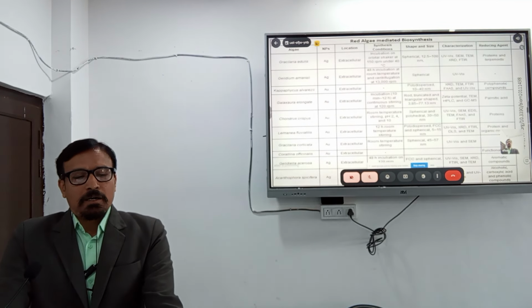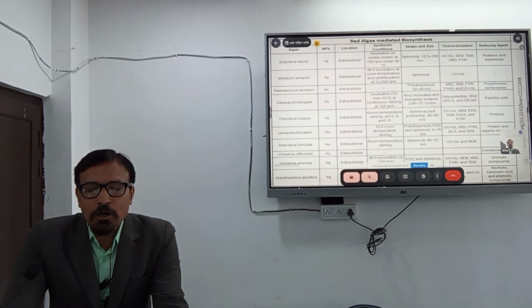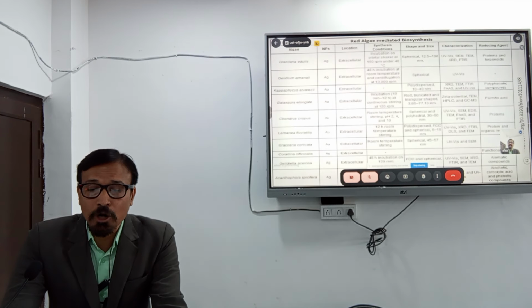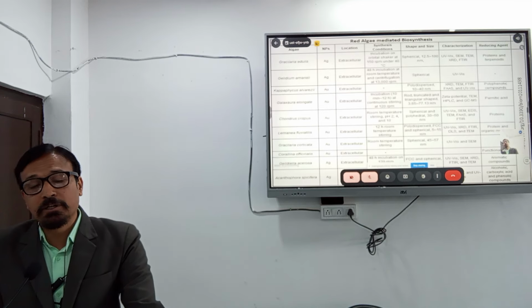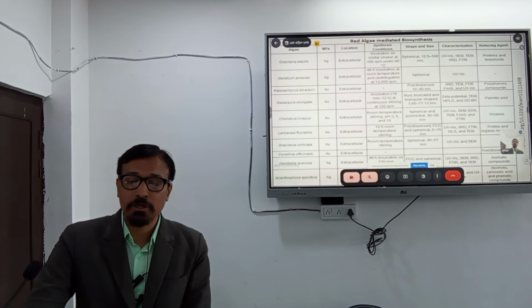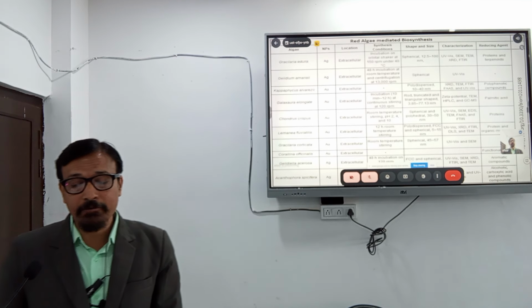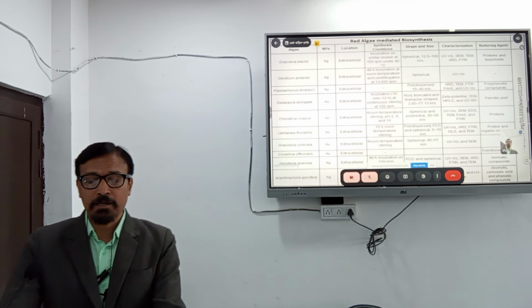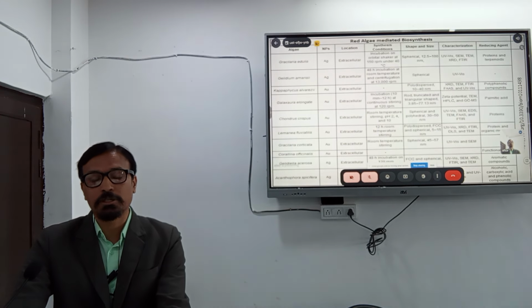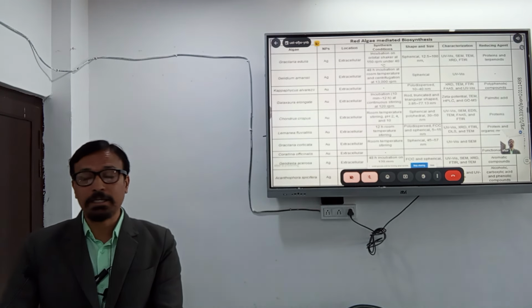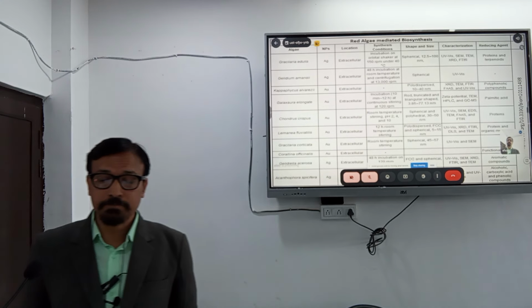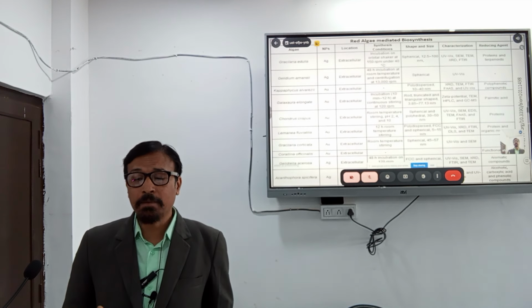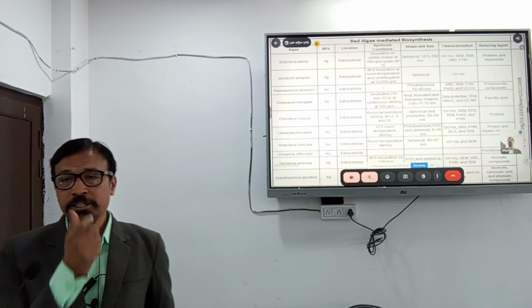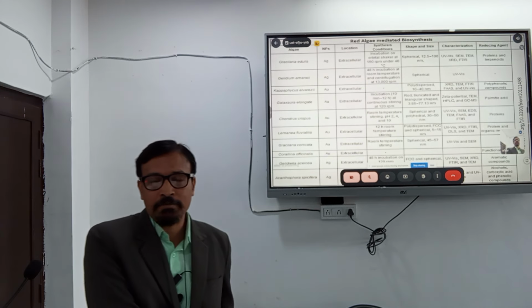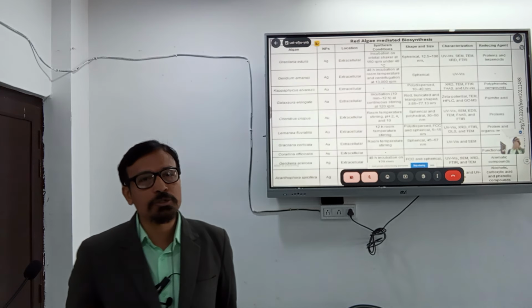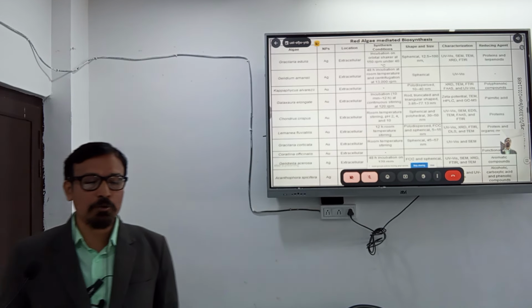Okay. And with the Gracilaria elongata, we will have rod, truncated and triangular shaped nanoparticles in the range 3.85 to 77.13 nanometer, and the characterization of those nanoparticles with Gracilaria elongata is done by zeta potential, TEM, HPLC and GC, and this is the palmitic acid present in the Gracilaria elongata, which will reduce the ionic species of the nanoparticles.